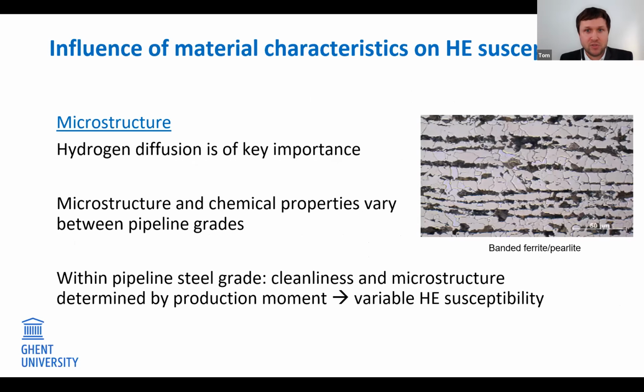Well, the diffusion is important. This is linked to the microstructure. Each microstructural component, phases and microstructures, they show a different behavior when exposed to hydrogen. Absorbed hydrogen atoms can diffuse in the steel, and they can get trapped. They can get trapped in a reversible or irreversible manner at trapping sites, at defects in a microstructure. For instance, grain boundaries, dislocations, or other metallurgical defects, for instance, non-metallic inclusions, precipitates, or regions of hard microstructures or segregation lines.